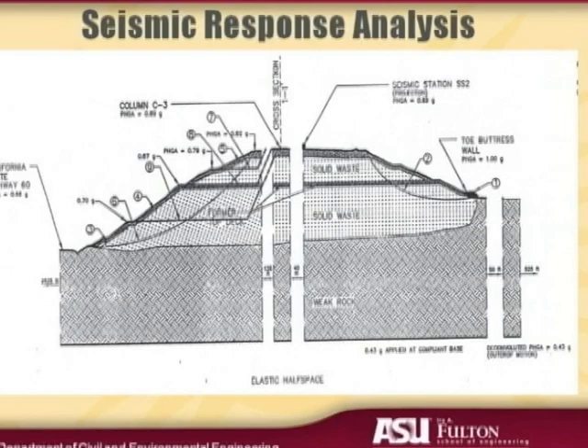But look over at the right side. The highest acceleration in all our analyses was the toe buttress. And that's what our structural friends would call hogging the load. The toe buttress was a very stiff element within this very soft and ductile waste mass. So when this thing starts to shake back and forth, the stiff member attracts the most load. So the peak accelerations in that toe buttress were always the greatest, not necessarily good news for the people living on the south side of the landfill.